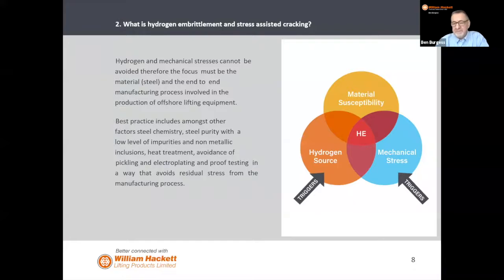We believe there are 3 areas of focus here. The hydrogen source in the bottom left cannot be avoided. We have to plan that corrosion is going to take place. At the right-hand side, the mechanical stresses of the load will always be applied to the product. It's what it's designed for. That cannot be avoided. The only thing that you can control is the material being used and its susceptibility to hydrogen embrittlement and the other pressures exerted on it offshore. So this comes back to the steel making process, the raw material, the tempering, and all these other processes. We will go into that in more detail if you wish in the Q&A with the panel. We believe that you have to start with material susceptibility. It is the only area that you can control.